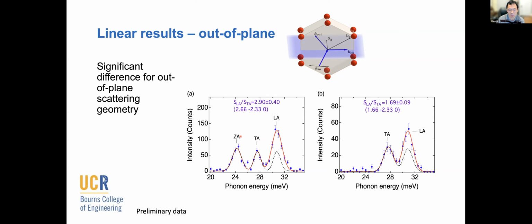One thing to notice is we do see the ZA mode, which is forbidden for this geometry, but we were able to triangulate this to a multiple scattering process, which is not part of our measurement here. And we have confirmed we do not see multiple scattering for the transverse acoustic and longitudinal acoustic modes. Okay, so that's interesting, but this doesn't provide us enough information to understand what is going on.